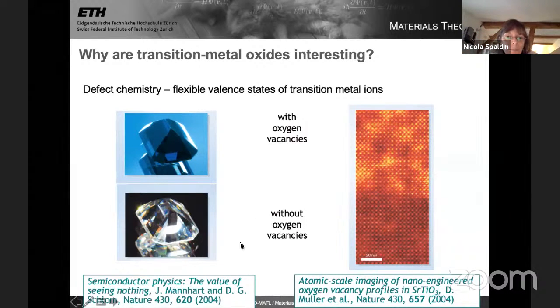And here's just an example on the left. This is perhaps the simplest complex oxide. It's strontium titanate, a crystal of strontium titanate. The bottom picture is just a photograph of this crystal, sorry, I didn't put the scale on here, with a very low oxygen vacancy concentration. And in the upper picture, this crystal has been annealed in nitrogen in a reducing atmosphere, so it has a lot of oxygen vacancies. And you can see right away that the optical properties change completely, it changes color. This is a very dramatic change.